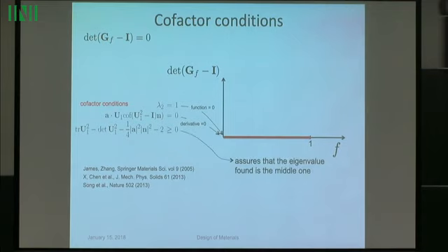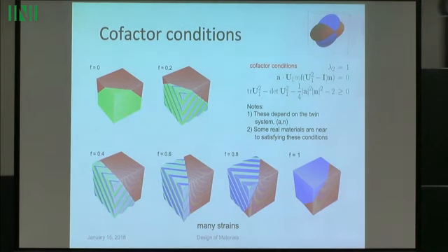So, can real materials satisfy these conditions? This would be quite striking because you can vary the volume fraction continuously from 0 to 1, and in every case you have a low energy interface. First of all, look at them theoretically. I'm varying the volume fraction from 0 to 1, and in every case, you can reduce the energy in the transition layer to 0 by refining the twins.